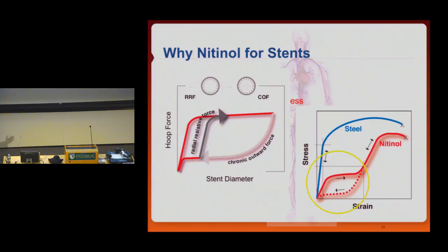And the important thing with self-expanding stents is that the stent should always be a little bigger than the vessel itself. So for example, a 10 millimeter stent you would put into an 8 millimeter vessel. So when you unload the 10 millimeter stent, you have 2 millimeters to go until you hit the vessel, and then it sits there. And at that point, it exerts this very low force. It tries to get bigger and exerts a certain force to the vessel. And we call this force chronic outward force, and that's very low.